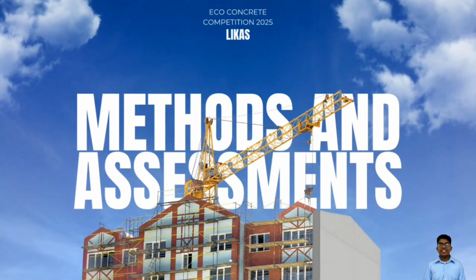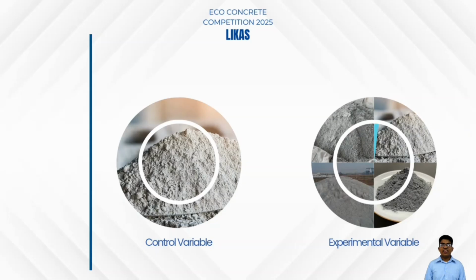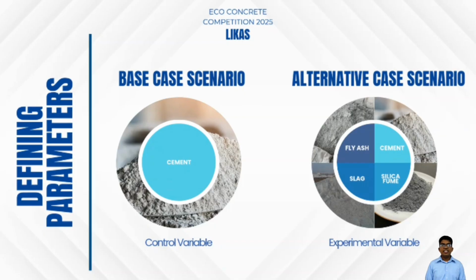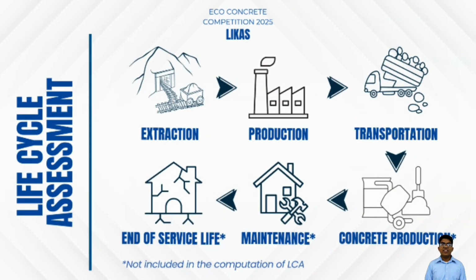Before we move to the two phases, we first define the parameters and methodology used in the study. The base case scenario, which acts as the control variable, uses cement as its binder. Meanwhile, the alternative case scenario, which acts as the experimental variable, utilizes fly ash, slag, and silica fume as partial cement replacement. Our LCA focuses on the cradle-to-gate analysis: extracting raw materials, producing them, and transporting them to the batching plant. For succeeding phases, concrete production, maintenance, and end-of-service life were excluded from the analysis.